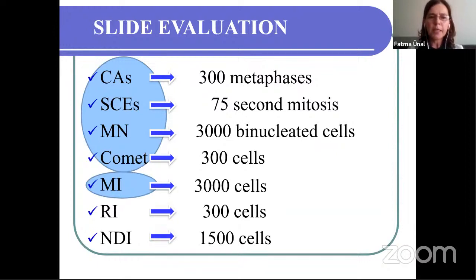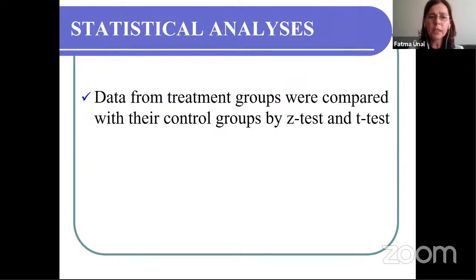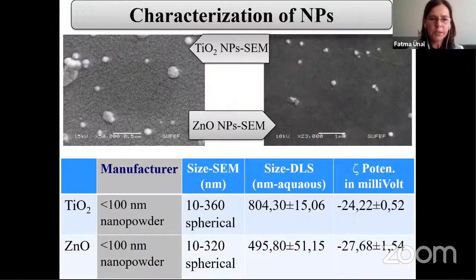To determine chromosome aberrations, sister chromatid exchanges, micronucleus, and DNA damages, slides were evaluated by examining a large number of slides. In addition, mitotic index, replication index, and nuclear division indices were also determined. Data obtained from treatment groups were compared with their control groups by using statistical analysis. What we have observed in this study: here we see some characteristics of nanoparticles given by the manufacturer. The other characteristics were determined in this study.